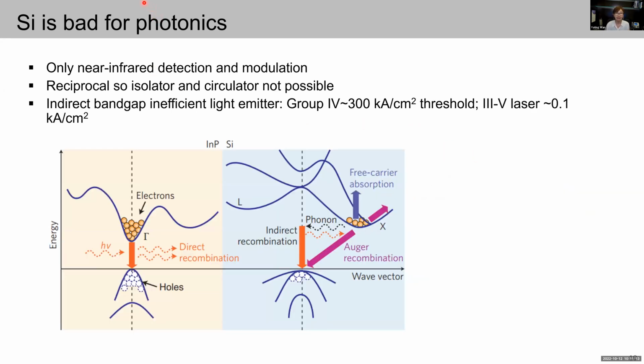However, in some aspects, silicon is a bad material for photonics. Silicon is an indirect bandgap material, so it's not a good light emitter. Actually, over the past 20 years, the best group 4 material laser has a threshold current density as high as 300 kiloamps per centimeter squared, which is more than an order of magnitude higher than what can be achieved in direct bandgap III-V material. Also, devices made from silicon and germanium can only cover modulation and detection for wavelengths around the near infrared, but are not suitable outside that range. Silicon is reciprocal, so isolators and circulators are not possible. All of this makes silicon germanium unsuitable for high performance lasers or amplifiers.